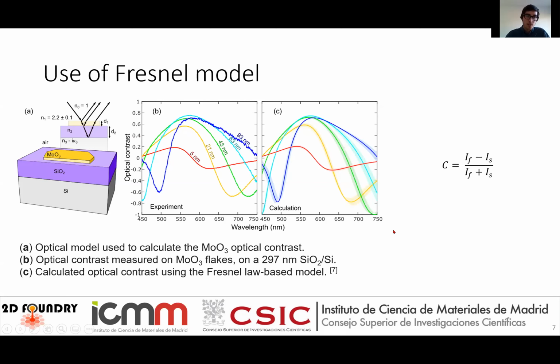This optical contrast, which can be calculated with this Fresnel model, is shown in the C image, and these ones are of the same flakes. And as you can see, there's a little bit of offset between the two figures. It fits very well. In fact, this method has an uncertainty of 1.2 nanometers for a 297 nanometer silicon dioxide substrate.